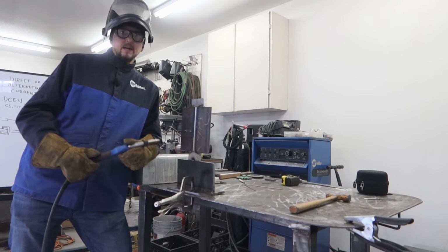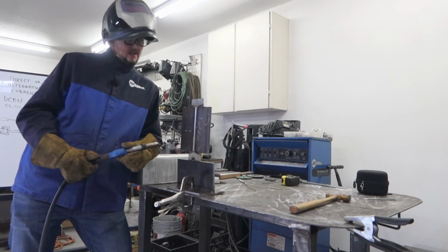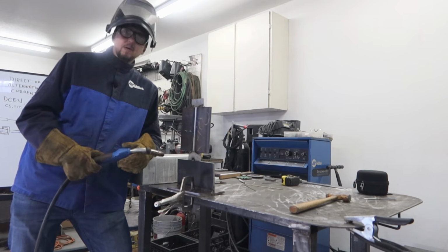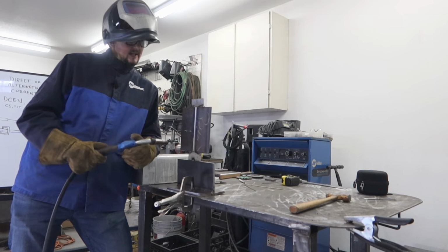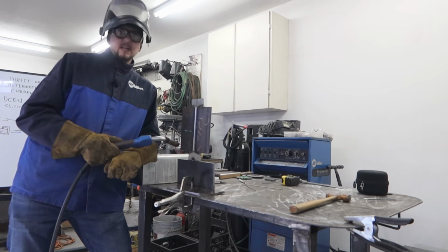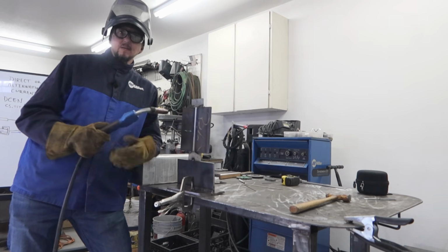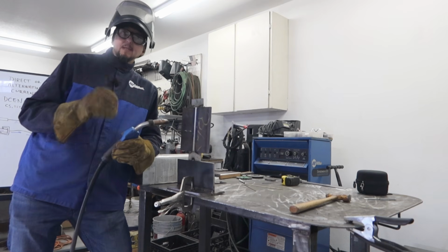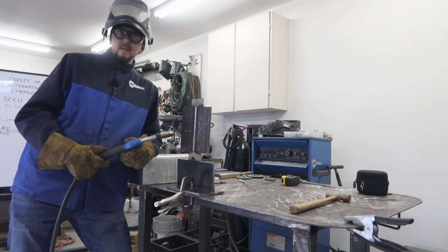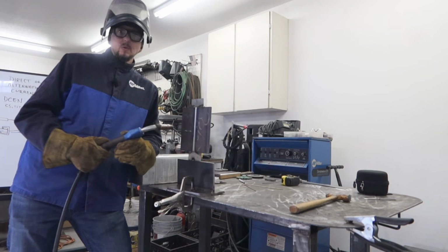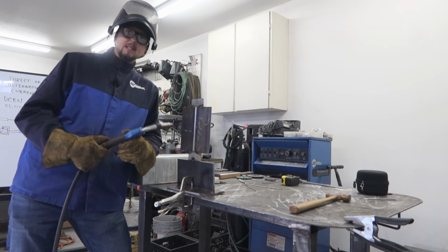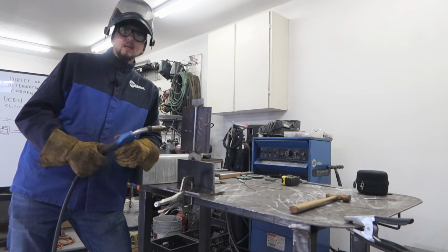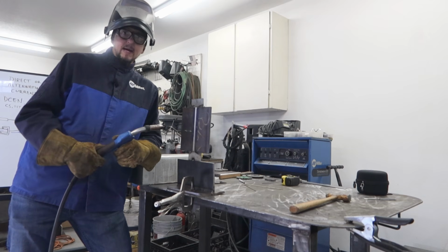You won't get what you want out of your weld if you're not comfortable. Okay, so let's go ahead and give it a shot with the root pass. At this configuration, in terms of my 3/32 root opening and my maximum 1/16 of a root face, I'm at 17 volts and 170 wire feed speed for my parameters on the root pass.